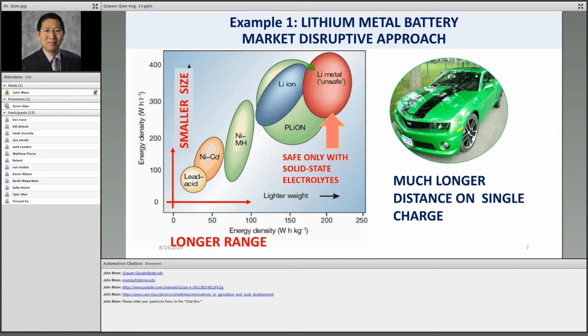But the problem with lithium metal is lithium dendrite growth. That can cause issues, both safety and also capacity decay and reduction for lithium metal batteries. That's why liquid electrolyte will not work for this type of battery. Only solid electrolyte will work.